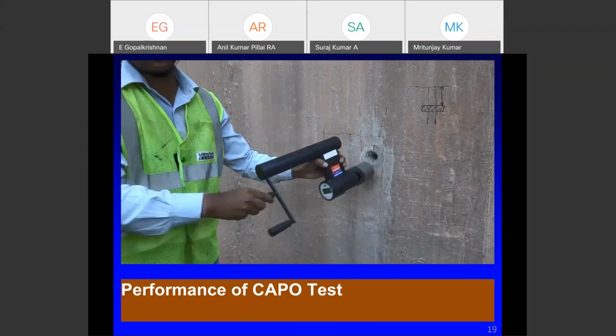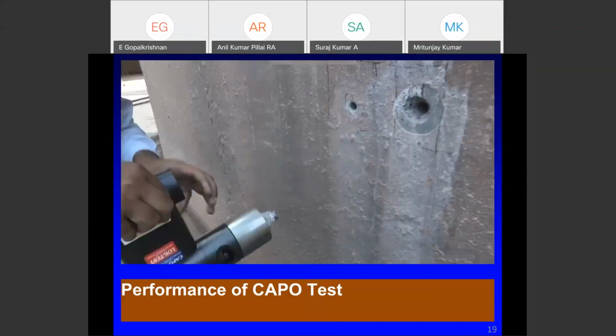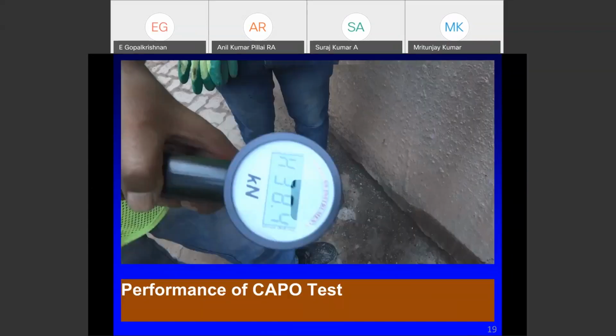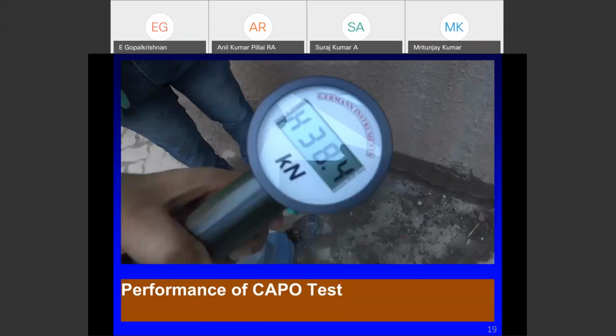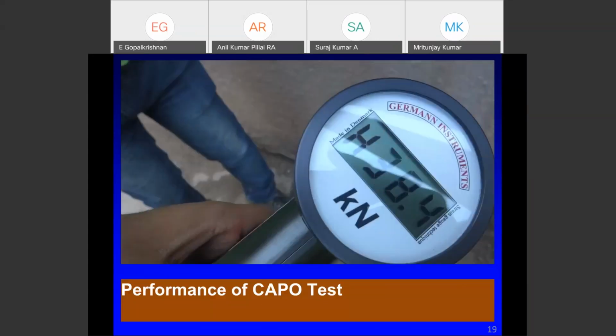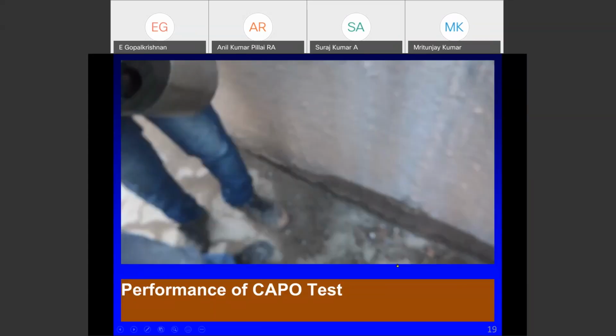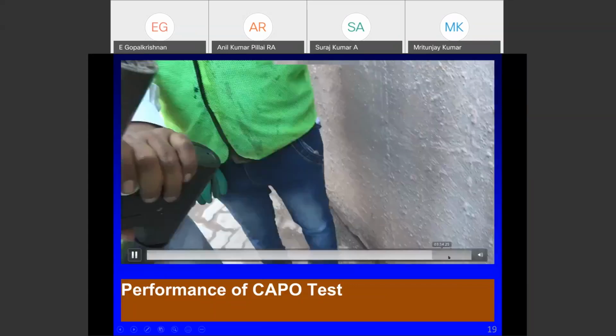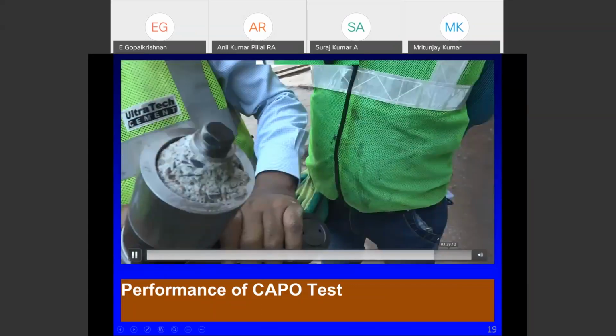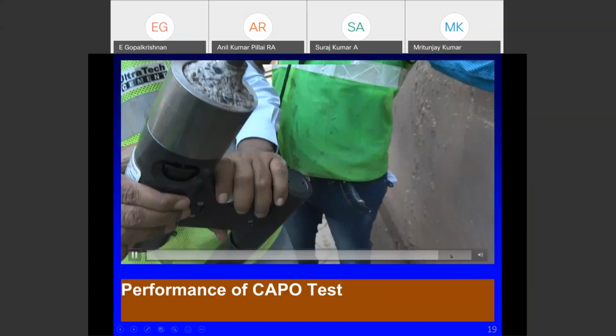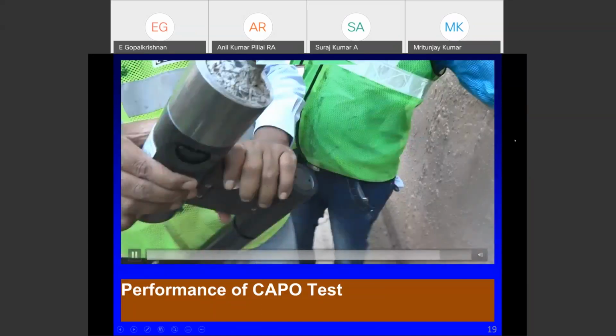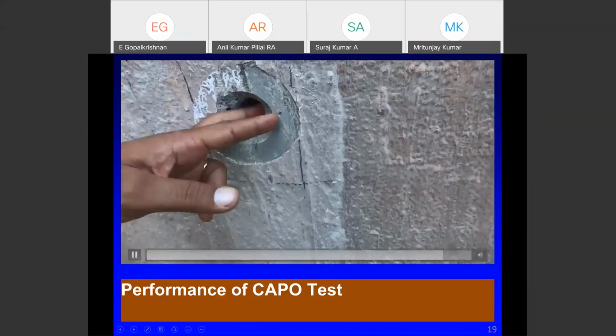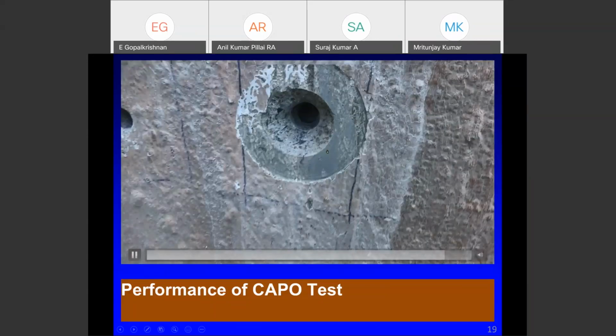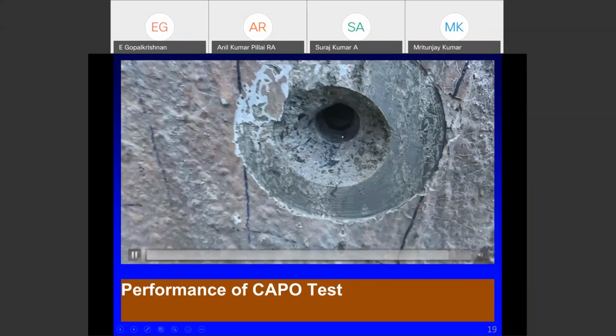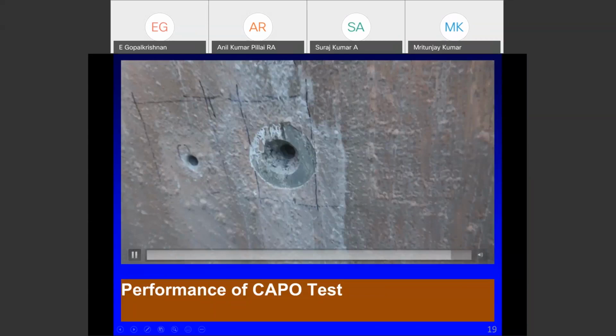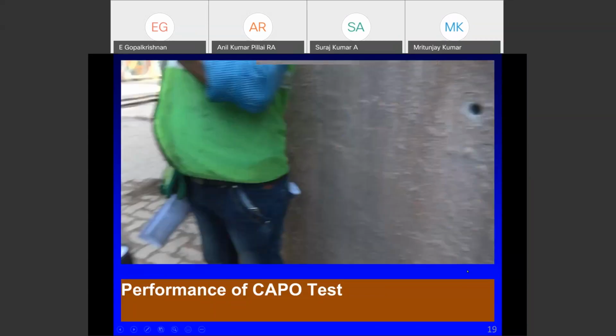Yes. Now it has achieved the maximum force. 38.4 is measured. So if you see, the cone is broken, and we can see that in place also the damage is very, very minimal. We are able to repair it with an equivalent strength of concrete mortar. The damage is very less.